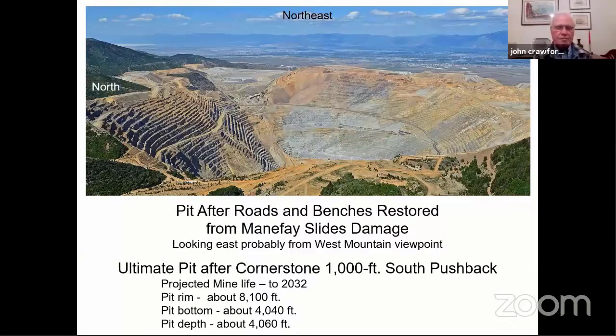That concentrate, excuse me, as well as the tailings, are pipelined over to the Great Salt Lake, and there is a flash smelter there that is probably 4 or 5 generations from the original American smelter that was built there in the early 20th century. And so at that smelter, they produce a conventional copper anode, which contains all of the precious metals and copper related byproducts.